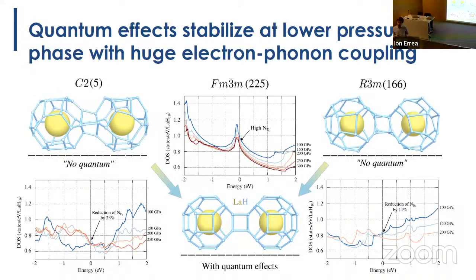Here we see in the density of states that you can keep a high density of states by considering these effects. If you distort the structure, this is lower. So somehow you are opening gaps. This is not an insulator, not a metal-insulator transition, but effectively you are opening some gaps when you distort. So it has an impact on the electronic structure. Yes.